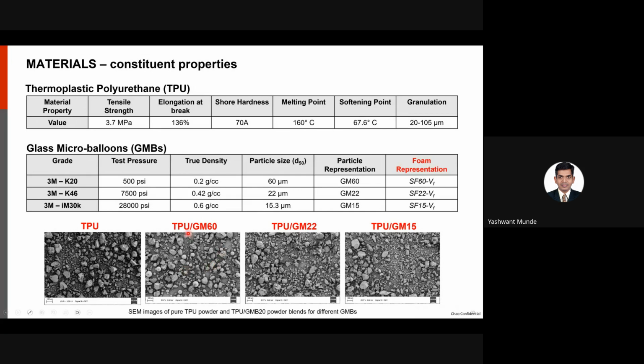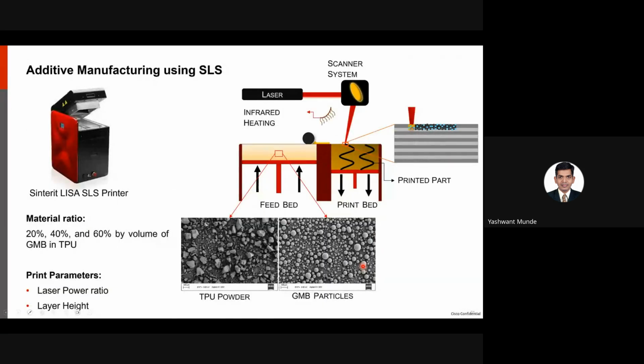So when we combine or just mix them, TPU and GM60, the GM60 particles are comparable in size with TPU, whereas the 22 and 15 are very small compared to the TPU powder size. So keep this in mind, because we'll talk about that later on, the effect of particle size on the foam properties, morphology and property. Right.